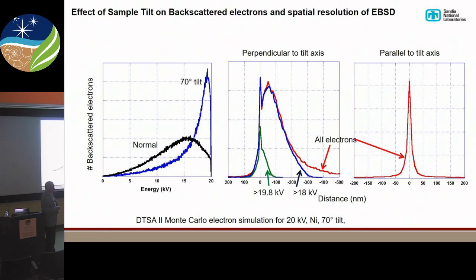Now the only difficulty is that because we're tilted to some high angle, we do get parallax down the tilt axis. So our resolution down the tilt axis is worse than across the tilt axis. But again, in normal mode, 50 nanometer resolution is not that difficult on a modern system. And with other techniques, like TKD, we can go down to 2 nanometers or so. I'll show you some examples later.